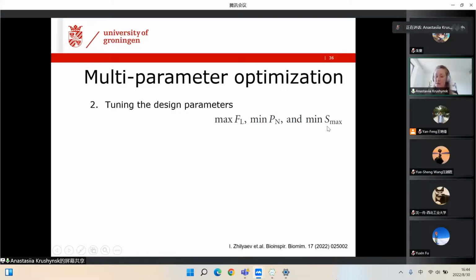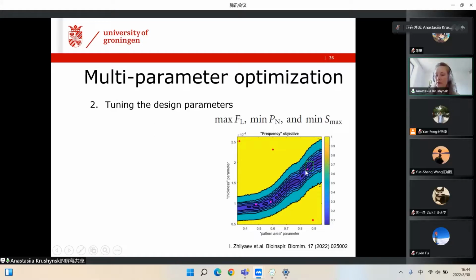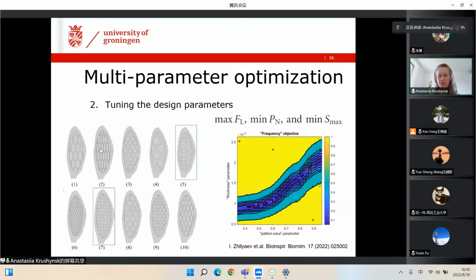For that, we use the results of the first step and focus on this small region, which is highlighted in dashed green, for which we are already close in terms of frequency to the resonance. Yes, this means that being in this region, we fix two parameters. This is thickness and pattern area, and change other three parameters of the pattern to achieve our goals. And within this small region, we can obtain quite different designs. So here you can see an example of 10 possible patterns, 2 of which actually satisfy the condition. So they indeed show that the lift is maximized as compared to a reference, and sound has minimum value.